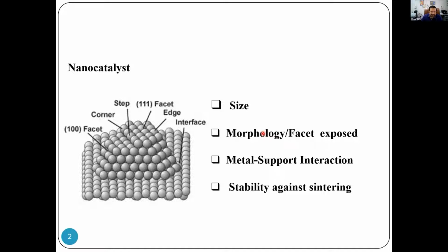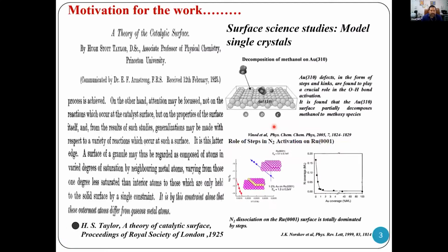Along with that, one of the areas that has recently emerged is to look at the morphology and facet dependence. So if you look at a nanoparticle, you can see that there are several active sites that can be possible. One is a terrace kind of morphology, which is generally formed with a 1-1-1 facet. Then you can also have a step site, corner atoms, kink atoms, and metal support interfaces. So what I'm going to talk to you about in this particular session is trying to look at catalysis with an angle of morphology and facet dependency.